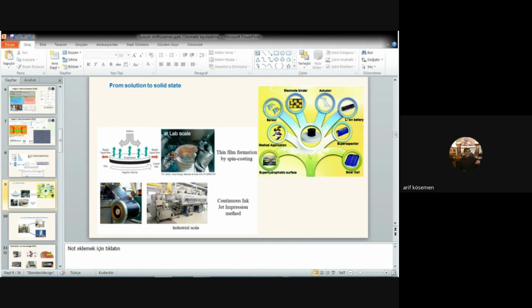And this is an example, thin film formation by spin coating. You can easily dissolve this material in a solvent, and you can coat any substrate with the spin coating method. If you want to move to industrial scale, you can use slot die or inkjet printing methods. These are very easy and low cost production methods. You can get large scale devices with these coating methods, with these conductive polymers.